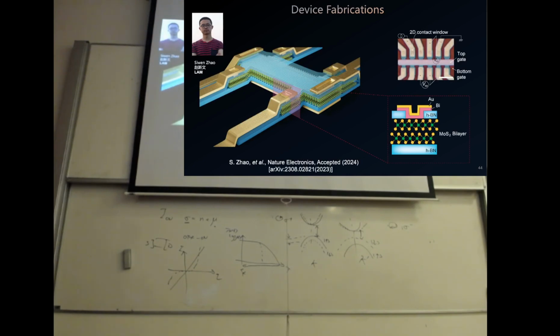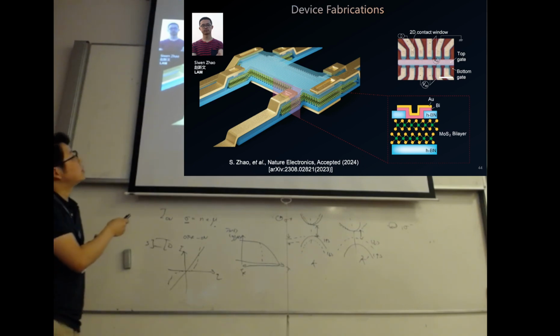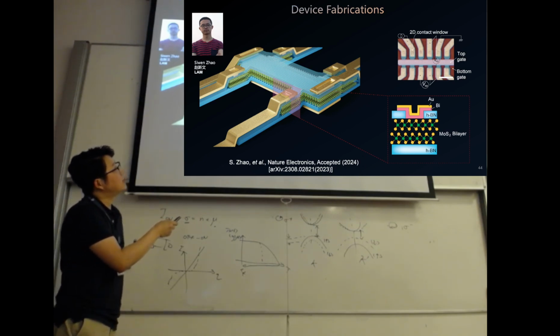And here I would like to share with you some of our results from my own group. Combining all these techniques from literature, there is actually a way to manage to have ohmic contact in MoS2 at very low temperature, down to a millikelvin. The method is not secret at all, we just have to combine several tricks together at one time. First of all, the device has to be made in a glove box, to avoid any kind of moisture or adatoms. And second of all, you have to use a window contact method.